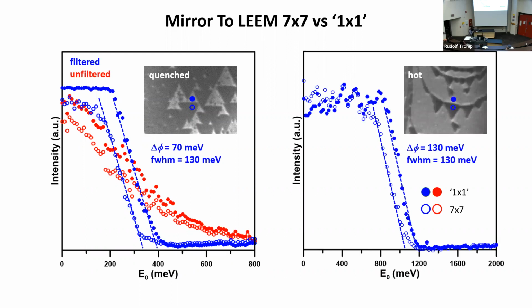Here we do it again. This is a silicon (111) surface at high temperature. The black triangles are 7 by 7. I've showed this before. The dark circles are 1 by 1, and we measure a shift in this potential, which means there's a difference in work function. The electrostatic potential in these 2 phases on the sample is different, in this case by 70 millivolt. Here, what did I say, 130 millivolt, right? So these are 2 different atomic structures, and they have a different electrostatic potential associated with them, which we measure here. Again, we can measure that on areas as small as 10 nanometers or something.